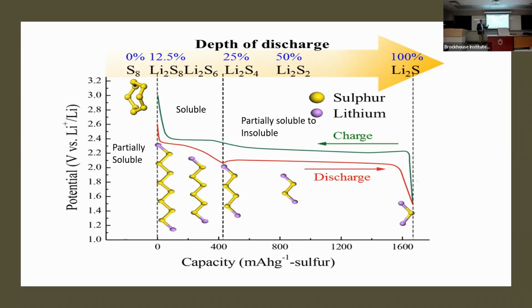It will still beat the lithium-ion battery. Yeah, without any problem, at a lower cost, without need for cobalt, substitute cobalt with sulfur, for example, or nickel. Yeah, and the price of nickel is going to go really high because the demand for it is going to be so high as the pressure to decrease the amount of cobalt in the lithium-ion battery gathers pace, nickel will increase. Yeah, which is good for Canada because Canada has a lot of nickel resources. Yeah, of course.